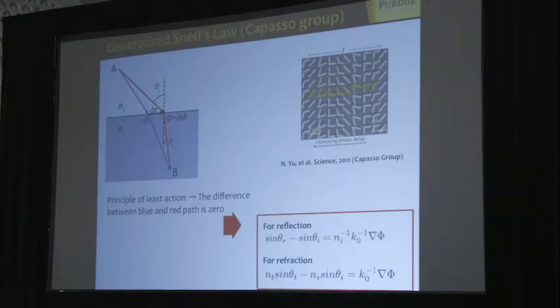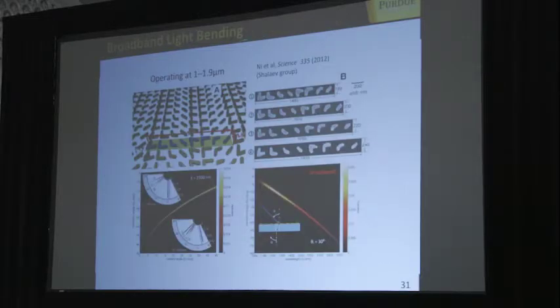Federico did it for mid-infrared. So we followed up and did it for telecom wavelengths. And to give you the idea, the size of the antennas is 30 nanometers thick, 50 nanometers the size of the arm, whereas the operational wavelength is 1.5 micron. And sure enough, we obtained this anomalous refraction, which depends on the type of antennas we use. You could send the beam in any direction you want.